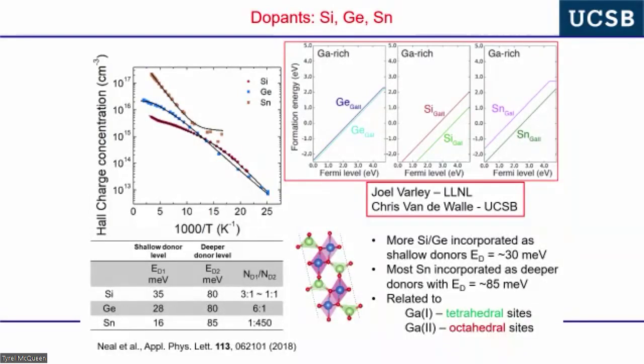Silicon doping seems to be the most favorable dopant, but tin doping, which is where we've done a lot of work, is a very nice donor in MBE growth. And it turns out for what we do, an 85 meV donor is fine. And this just goes through some of the issues in the donors, okay? And I took the slide out and now I regret it.